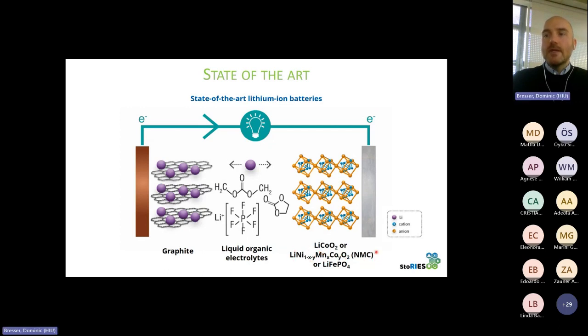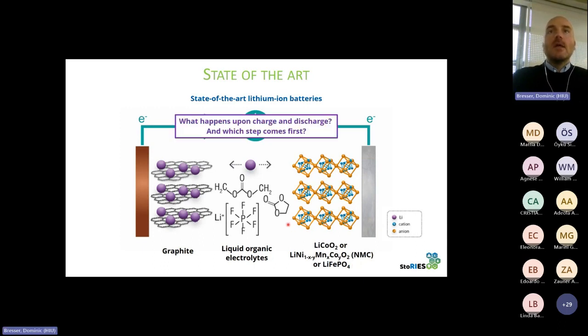Something that is abbreviated NMC or NCM frequently, where part of the cobalt is replaced by nickel and manganese, or in fact not part anymore, but 90 or 95% frequently. So they are becoming nickel-richer now. And lithium iron phosphate, that is now dominating, especially in Asia, in vehicles that are produced in Asia and then shipped to Europe at some point. So this is basically the state of the art.